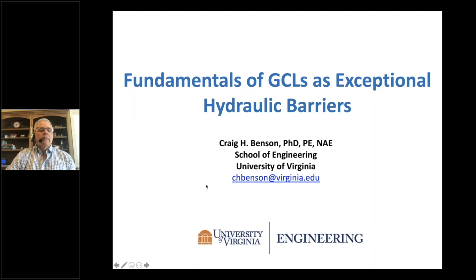Herman Nigg: will you include the difference in performance between sodium and activated sodium bentonite in your coming webinar? I wasn't planning on that, but I will. That's a great topic. Sodium activated bentonites and conventional sodium bentonites can behave almost identically. It's really driven by how much residual divalent salts are remaining in the activated bentonites. The mineral itself is similar, but I'll build that in. We get to the chemical compatibility one, webinar three. I'll build that in. Great idea.